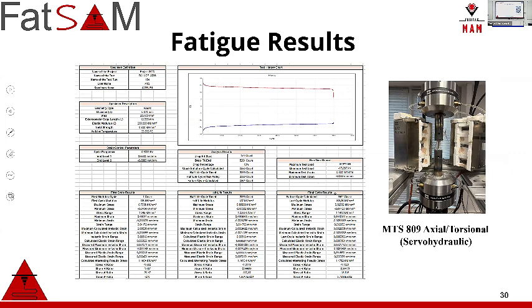So these are the basic fatigue results we have got. Our software can provide history of stress and cycle, or strain amplitude and cycle. Also, we have any kind of strain control parameters. We have in-touch extensometers, 3 thermocouples connected to threads at the center of the materials, plus or minus 3 Celsius, and cooling in the grips. This is not a mechanical grip, it's a hydraulic grip. For high temperature applications, it's a requirement to use hydraulic grips. You cannot do high temperature mechanical tests with mechanical grips. In a force control test, you have advantages. You don't necessarily need to connect thermocouples, or you don't need to use in-touch extensometers. And also just per cycle results, half cycle results, final cycle results.